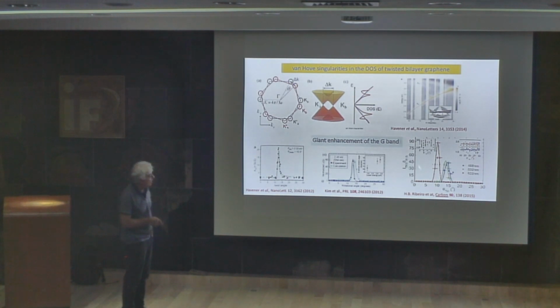That's why, in this case, I was lucky. This is the red laser, this sample at 10 degrees. I could see that when the laser is in resonance with those singularities, I have a resonance effect, and the peak becomes very strong.